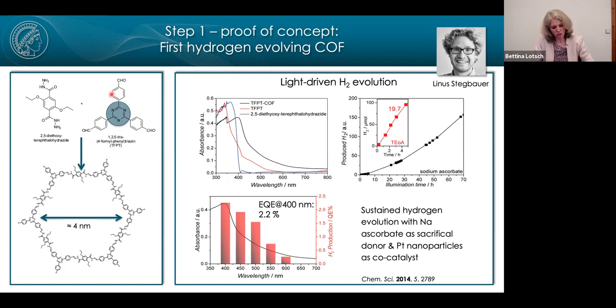This first photocatalytically active COF was a hydrazone-based COF. Here you see it's a mesoporous system based on this triazine building block. In a nutshell, we could show that the system is active for hydrogen evolution in the presence of a sacrificial electron donor and the co-catalyst platinum. And we achieved quantum efficiencies around 2%, which were at that time competitive with those of carbon nitrides. So that was the first proof of concept.